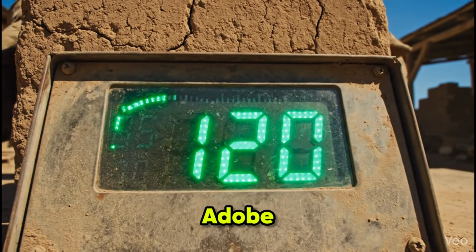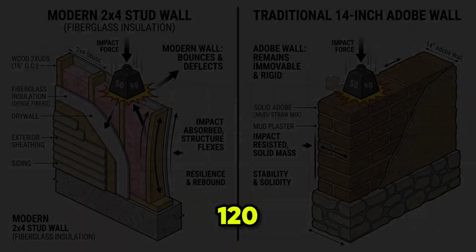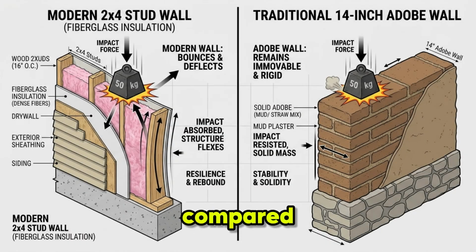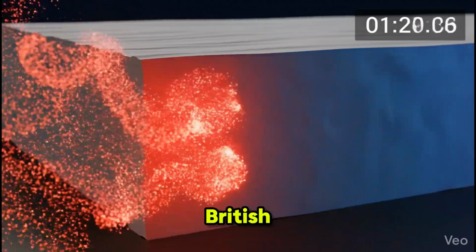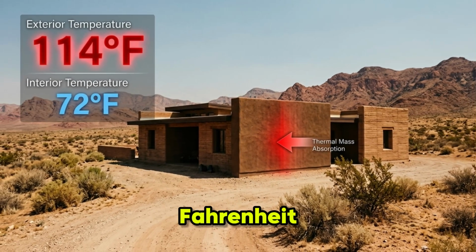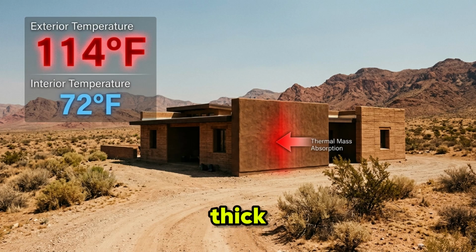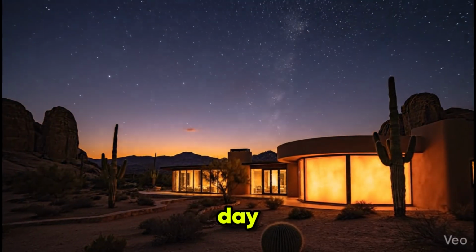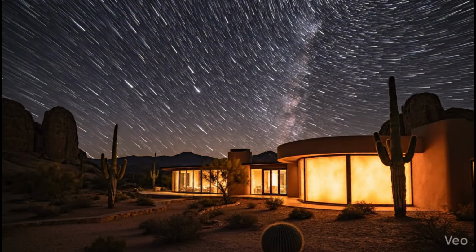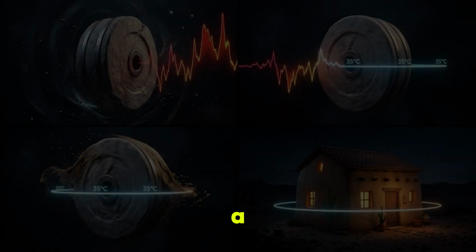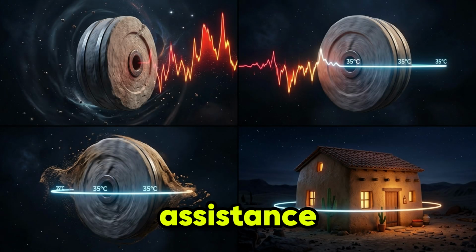The thermal performance of adobe comes from its density. A standard adobe brick is dense, approximately 100 to 120 pounds per cubic foot, compared to about 30 to 40 pounds per cubic foot for a framed wall cavity filled with fiberglass insulation. That mass has a specific heat capacity of roughly 0.2 British thermal units per pound per degree Fahrenheit. A typical 18-inch thick adobe wall contains enough thermal mass to absorb the entire heat gain of a summer day and release it through the cool of the night, keeping the interior within a few degrees of a stable mean temperature without any mechanical assistance.